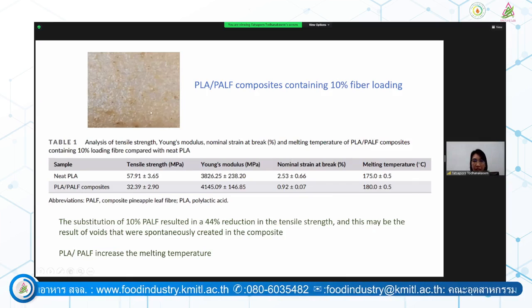However, when we look at the Young's modulus and the strain at break, the strain at break is reduced. So it is more like the stiffness of the PLA containing PALF is better than just the PLA itself. The melting temperature is slightly higher when we mix with the pineapple leaf fiber. So basically the properties are better than the PLA, except the tensile strength, where we have to improve the treatment process in order to blend well with the PLA.